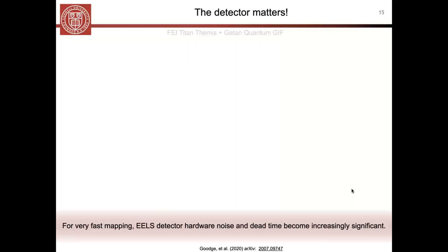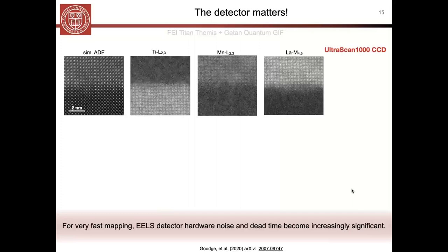And so at that point, the specific hardware that you're using is really going to start to matter. So for example, here is an atomic resolution map taken on one of our primary tools at Cornell, which is a Titan Themis at 300 kilovolts, using a Gatan Quantum GIF, and in this case, the detector is an UltraScan 1000, which is a CCD detector. And so it's a very nice atomic resolution EELS map. You can see that the stronger edges map very well, and the weaker edges, of course, map slightly less well, but it still looks very nice, and you'd be happy if you took it.